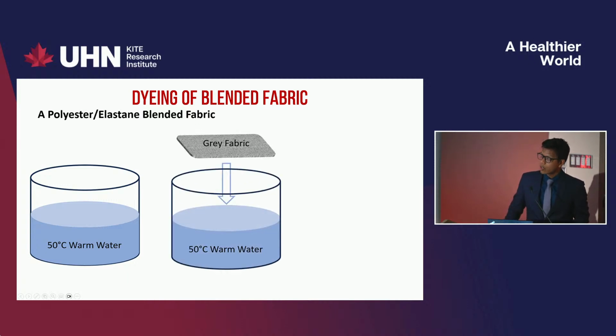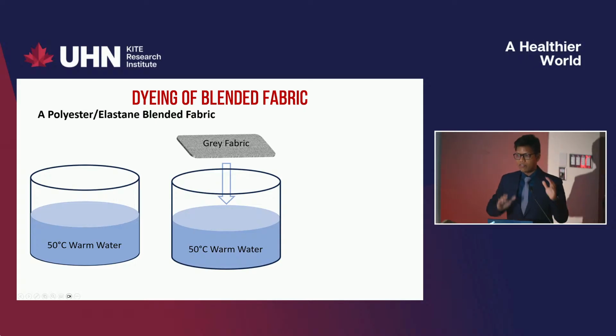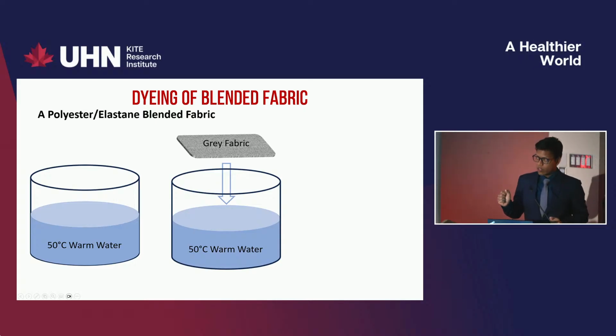Then in the warm water, we insert our gray fabric. By gray fabric, I mean the fabric I'm getting from the knitting department or the weaving department after the manufacturing of the fabric. One consideration for any fabric which combines elastane or spandex fiber is that the fabric needs to be heat treated. So we insert the heat-set fabric in 50 degrees centigrade warm water.